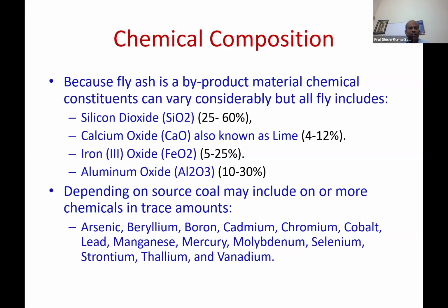And what is the chemical composition? Because fly ash is a byproduct, the chemical constituents can vary considerably, but all fly ash includes silicon dioxide, something like 25 to 60%, calcium oxide, 4 to 12%, iron oxide, 5 to 25%, and aluminum oxide, 10 to 30%. Depending upon the source coal, it may include one or more chemicals in trace amounts: arsenic, beryllium, boron, cadmium, chromium, lead, manganese, mercury, molybdenum, selenium, strontium, thallium, vanadium. So these materials are available in trace, small amounts in fly ash also.